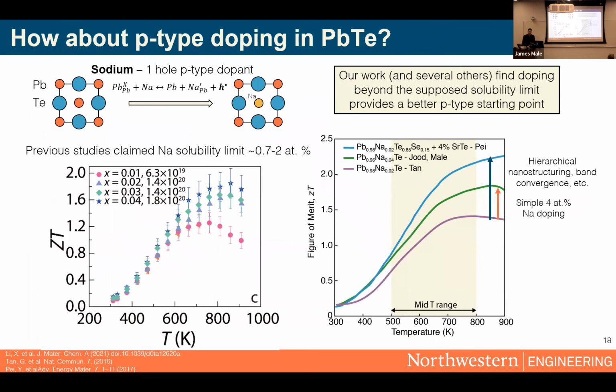So following up that N-type work, we did a similar project in P-type lead telluride. This oppositely doped sample is most commonly doped P-type using sodium, which should give you one hole when it replaces a lead atom in lead telluride. And this is kind of a legendary dopant.